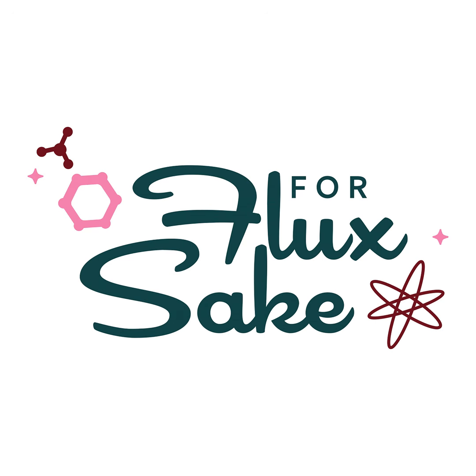What they should be doing, though, is that if you go to the cone chart, the second stage should be at 150 degrees C per hour to 1243 for cone 6. Okay, and whatever that is for Fahrenheit. I don't have the Fahrenheit chart in front of me. So you should be going 150 degrees C per hour to 1243. Is that what Bartlett does? No, it is not. Because in fact, they go to only 111 degrees C, 200 degrees F per hour to, wait for it, are you ready? Are you ready? 1222. The cone 6 temperature at the medium rate.